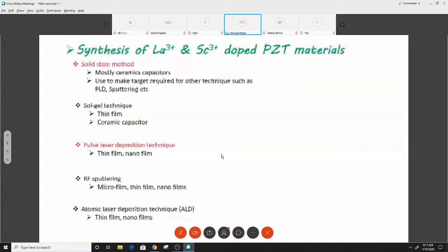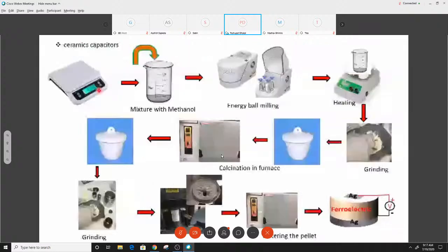Especially in the solid state method, we make a ceramic capacitor, and in the pulsed laser deposition technique, we make a thin film or nano film. This is the schematic diagram to make a ceramic capacitor. The required amount of elements are mixed with a solvent like ethanol or methanol. Then we put it for ball milling, for 12 to 24 hours, and that is dried at around 100 degrees Celsius. Then the dried material is ground and put for calcination at around 1000 to 1300 degrees Celsius.